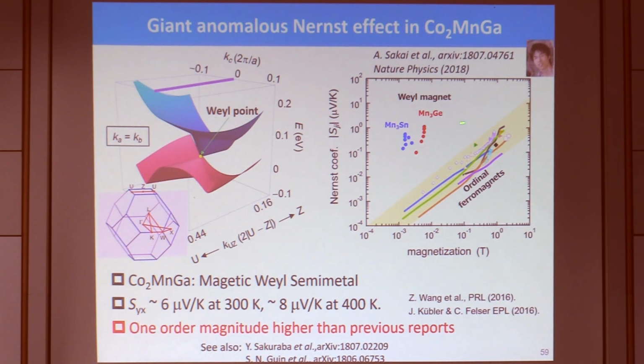We tried to apply this mechanism to ordinary ferromagnets to see if one can actually enhance their performance by designing the electronic structure. We found that Co2MnGa does have the Weyl point near the Fermi energy, and it turns out it does have a much larger Nernst effect than ordinary ferromagnets. It is actually one order of magnitude higher than the previous reports. So this tells us this is just the beginning of the story, and we hope we can enhance this number much further.